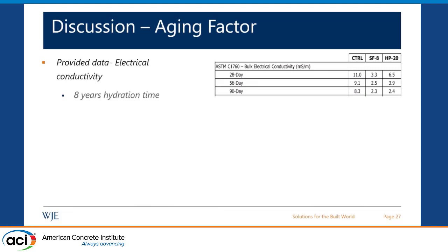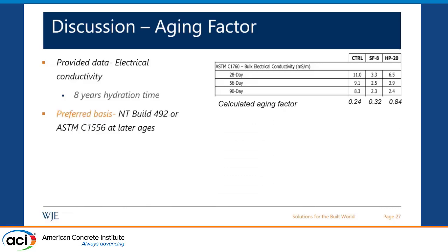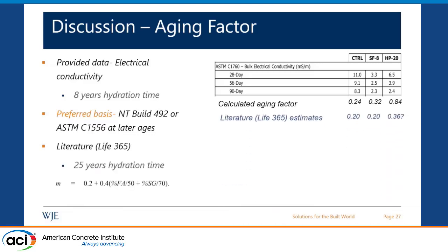The results I presented earlier are based on the calculated aging factor from the bulk electrical conductivity testing. However, because this is affected greatly by the chemistry of the pore solution, which has little to do with chloride transport in concrete, we would prefer to rely on NT Build results or ASTM C1556 at later ages. However, recognizing that that takes a long time and sometimes it's not feasible with new construction, we turn to the literature. So here, for example, I'm showing the value if we use the data presented in the literature and in Life 365 for the aging factor.